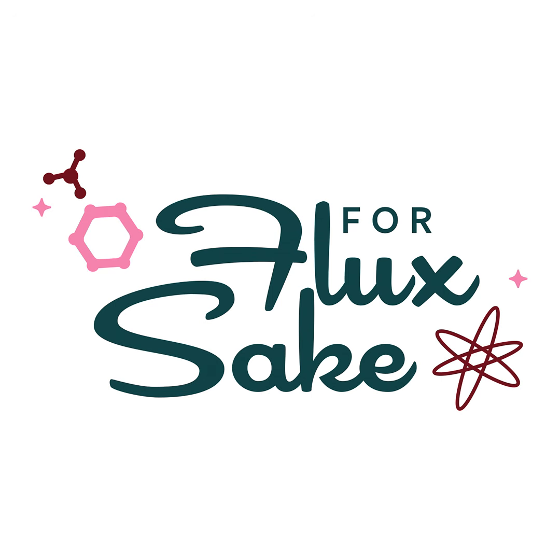Like I said, Ian, you want my fast firing program? I just told you. You go 300 degrees C. Sorry, you have to translate to F. That I'm not going to do for you. 300 degrees C per hour to 100 degrees under peak. Right. So my peak is going to be 1243. So 100 degrees under, that's 1143. And then I go 150 degrees C per hour from 1143 to 1243. And that's it. Two segments done. And that will get you there. And then just a natural cool. Yeah, just let it cool.